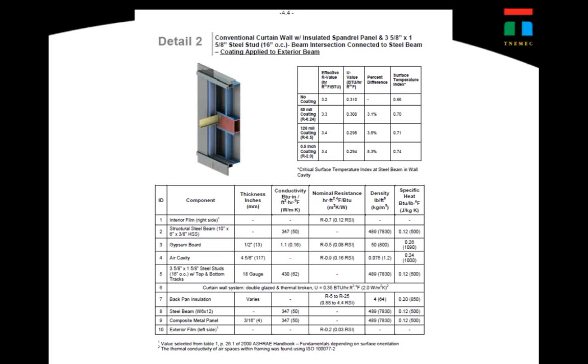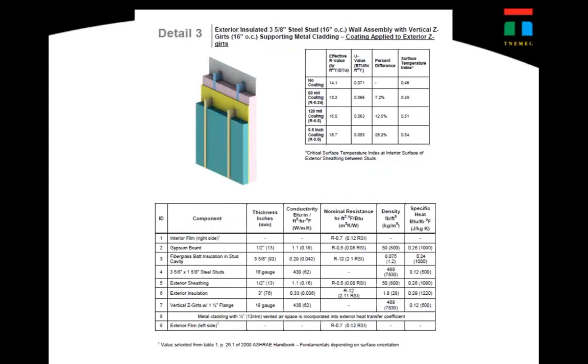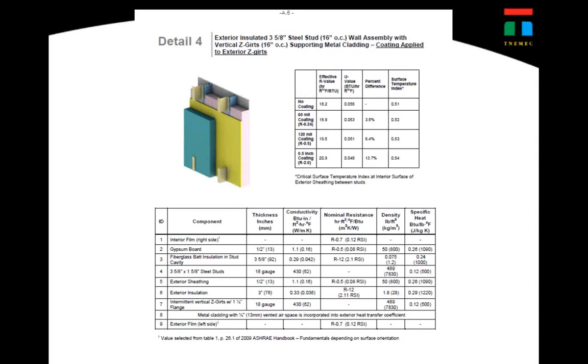And on this one here, you can see just that clip angle, that beam going through. We're at 0.7 on the surface temperature index at 60 mils. Well, 3.1% difference between the effective R value and the U value, obviously, but it's a very significant difference in the ability for this product to prevent condensation. And that's what Jenny was so interested in, is could they put a coating on the perimeter of a building that could slow transfer of energy, cold or hot, into a building so that they could prevent condensation from forming. So all of these details, they're obviously all here. I don't want to spend the entire time going through all of them, but the data is pretty interesting.